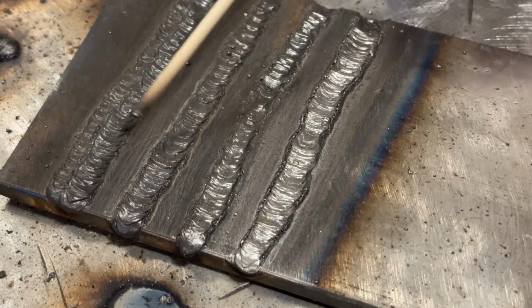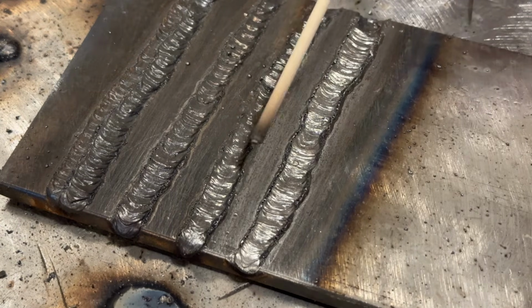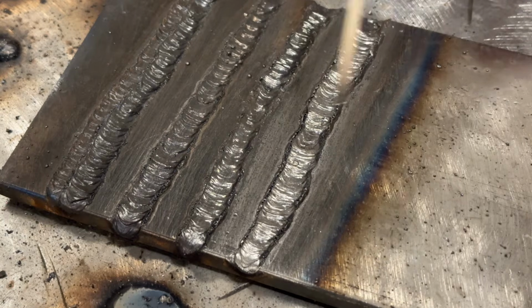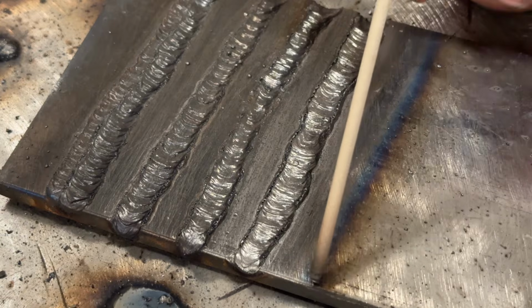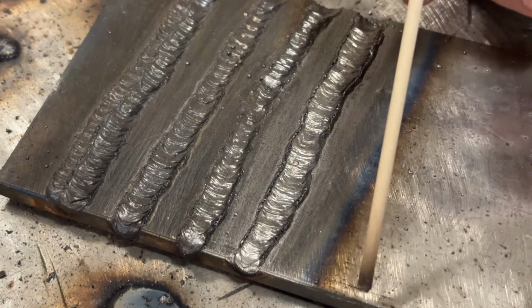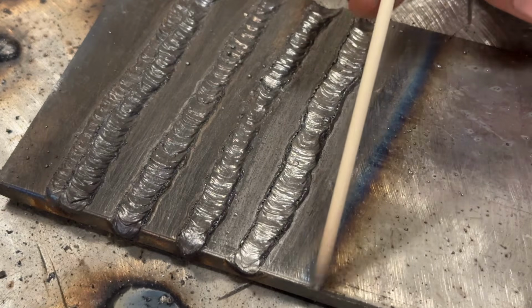Now, these welds I all did with 30% arc force, which is probably similar to what your welder naturally is if you don't have adjustable arc force. I upped this to 65%, which is what Miller recommends for 6011, 6010. And let's see if the weld pool looks different. So this weld I'm going to run pretty much normal. However, when I push the rod down to the plate, you're probably going to notice that the molten puddle gets longer in length and likely a little bit wider. I'm going to do a couple other minor manipulation changes. But you can see it's kind of putting a little bit more heat in. It's a little bit hard to tell though. The next weld is going to look a lot different.